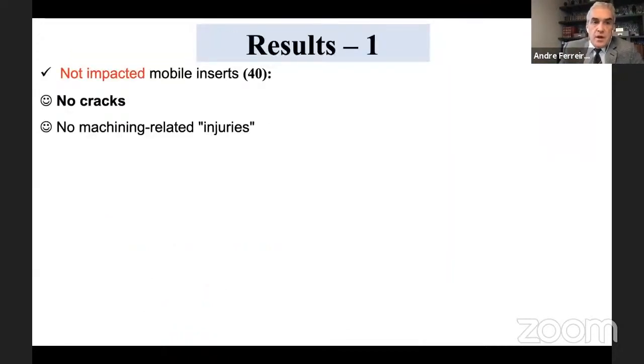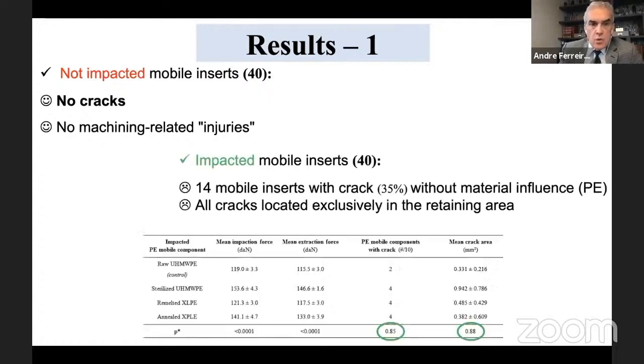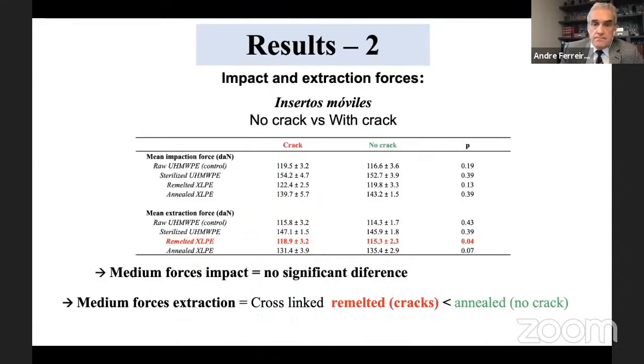First, if we compare the non-impacted mobile inserts without head, there are no cracks for all the series of standard polyethylene and cross-linked ones. When they impact the head into the mobile insert, there were 14 mobile inserts with cracks, but without influence of the polyethylene. Cracks occurred in all the polyethylenes, standard one, annealed one, and remelted one. No difference between all of them.